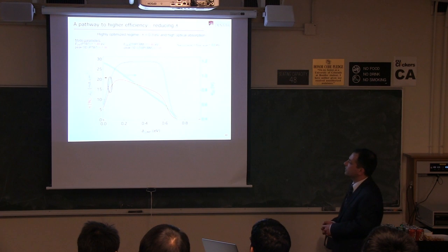But here's the bottom line. Now let's go into really good imaginary land and say that both of these materials have an optimal band gap of about 1.4. They're both very dense absorbers. So the peak optical density is 1 for both of them. They're both absorbing 90% of the light, so altogether you're absorbing 99% of the light. Stick with the very low reorganization energy, and what you get is that you could push the delta LUMO down to 0.2, and get efficiencies approaching 20%. This is not the highest efficiency we could attain. It's the highest we can attain with this material under optimal circumstances. There's still a lot more that we can consider to optimize. But that is one pathway to consider a 20% device that would meet the cost goals that we need to reach.